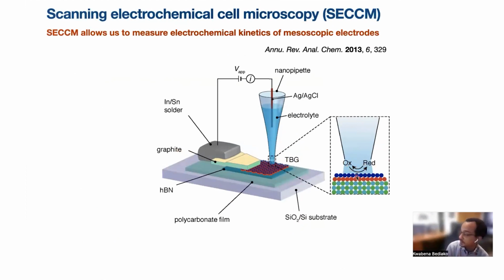And this is really nice because it allows us, in principle, to do spatially resolved electrochemistry. Typically, our pipette size is about 100 to 300 nanometers. And so the length scale that we're probing in these experiments is not a sub-Moiré length scale. It's an ensemble over the Moiré. But nevertheless, because of the size of the samples that we make, this is really convenient, because these samples are typically on the few micron scale.